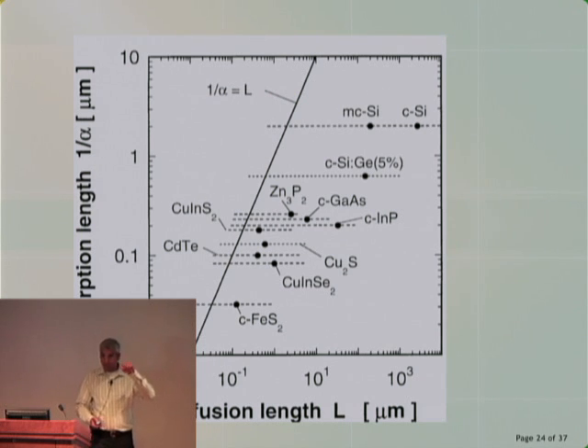So remember what I was saying before with silicon, one of the hurdles is that because we go thicker, we need to be more pure. Well, iron sulfide, we can do it at 20 nanometers, the same that you would do with silicon on the micron scale. And at 20 nanometers, that opens up a whole new possible door for processing, controlling self-assembled nanoparticles. You can do a lot more, but you can also worry less about the defects on the iron sulfide because the pathway for the electrons is so short.